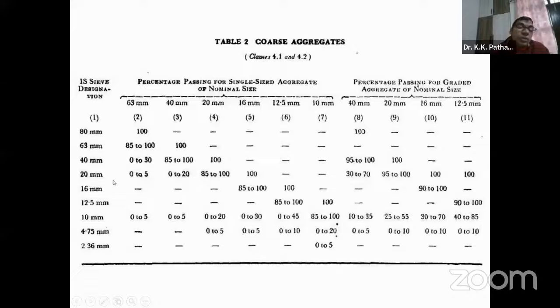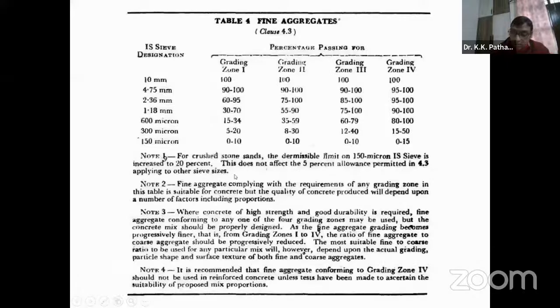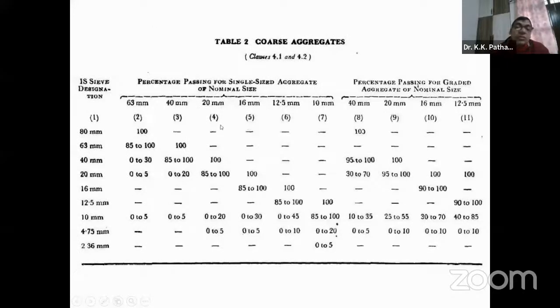These are what I was mentioning: your sieve analysis and gradation, we have to ensure that if we are using 20 mm aggregate, then 85 to 100% should pass through the 20 mm sieve. We should not use 40 mm or bigger than this. So these are the quality checks that we have to regularly make. Many times when I go to site, I find they are using coarser aggregate, more than 20 mm. Now you cannot expect the quality, because there will always be pores. How much sand will you add to fill those voids?